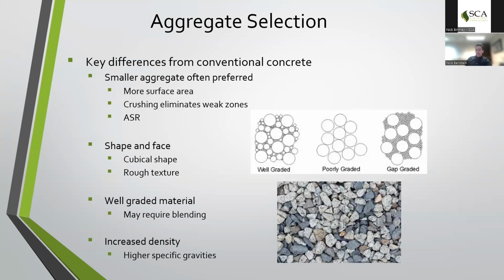Aggregate selection continues to be a major portion in helping support the well-designed SCMs. Good, well-graded aggregate can help achieve a lot of the things that we often have to overcompensate with paste for and help alleviate other concerns such as cracking and potential ingress and shrinkage. The key difference that you're also going to see from conventional concrete is smaller aggregates in high performance mix designs. This is most often an attempt to help provide that well-graded and essentially much more penetrated matrix within the concrete itself.